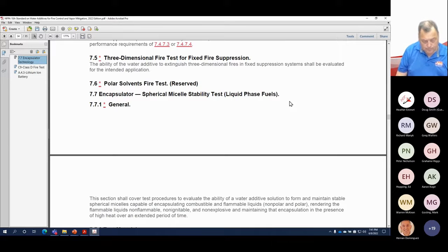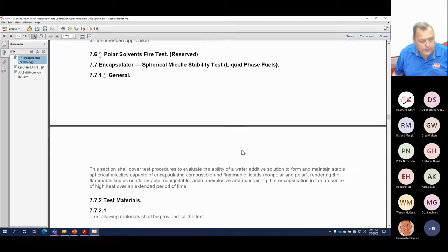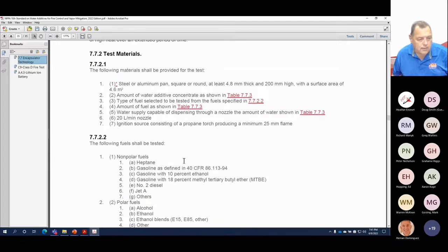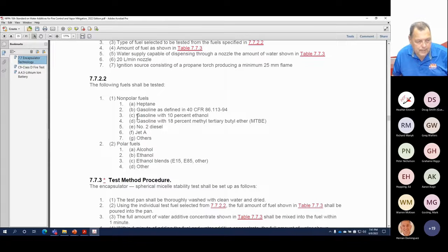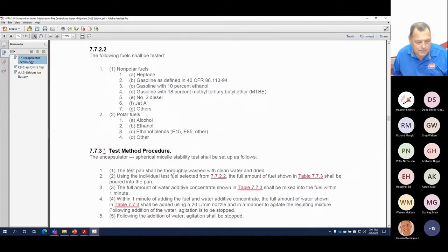This test measures, because what we're doing here is we're taking the test fuel, whether it's heptane, gasoline, diesel, and we shared this with Panasonic, and we said, you have a flammable electrolyte. Let's use your flammable electrolyte as the test fuel. So we take a test pan, we thoroughly wash it and clean it, we put the test fuel in, we add an amount of additive, and then we add water. And then within 1 minute, we put a torch to the surface of this, a 1500-degree torch.